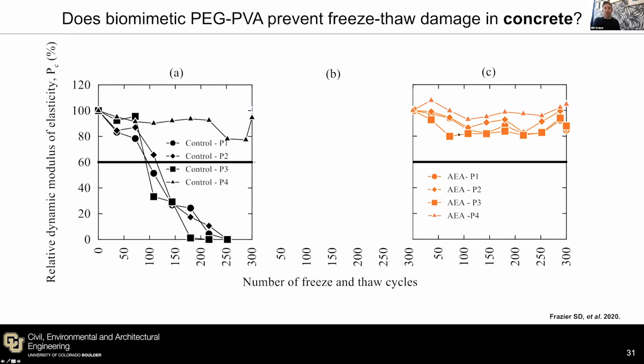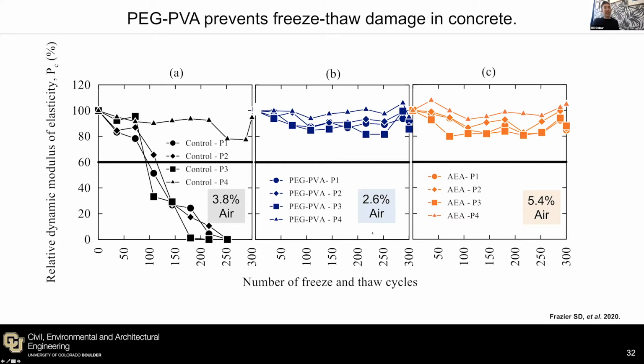We went ahead and put air into one of the samples. So we compared this to an air entrained sample. And we also found what we would expect to find, that the air entrained sample also resisted freezing and thawing. Nothing new here. But the really exciting finding was that our PEG PVA sample also exhibited enhanced freeze-thaw resistance,